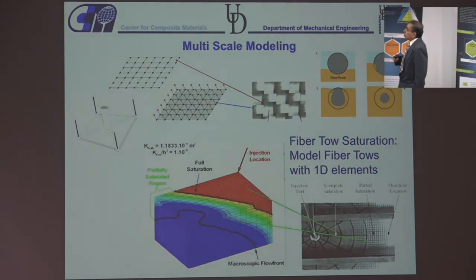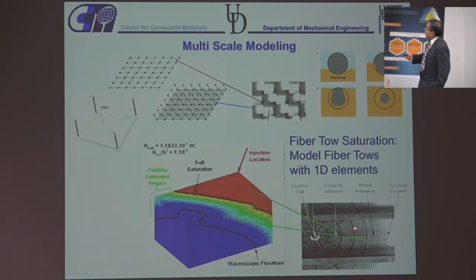Now we can use the same simulation with these additional elements. The only price we have to pay is we have to introduce a second permeability, one that is with the tows for these elements. So now if I inject the resin here, the red area is where the fill factors for one-dimensional elements and for two-dimensional elements is 1. That means they're all filled. Between the two black lines is where you have the regions in between the fabric that's filled, but the tows are not completely filled, and then this region is completely where there is nothing filled.